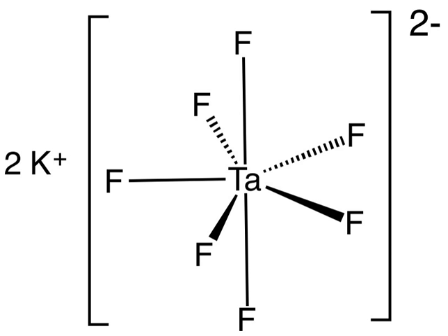At temperatures above 230 degrees Celsius this converts to beta-K2TaF7, which is orthorhombic space group PNMA. This structure also consists of potassium ions and the complex anion TaF7^2-. The structure of the seven-coordinate TaF7^2- units is essentially unchanged. However, the potassium atoms now exist in two environments where they coordinate to either 11 or 8 fluorine atoms.